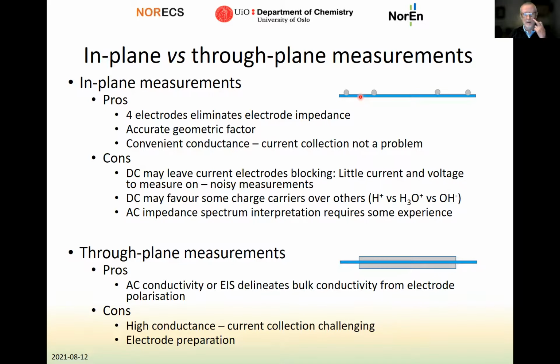So in an in-plane measurement, you can do a 4-electrode measurement. You supply the current here and here, and you measure the voltage here and here. This is a very well-controlled geometry, and it has several pros: 4 electrodes eliminates, in principle, the electrode impedance. It has an accurate geometric factor, and it allows you to measure with quite a convenient conductance range, so it's not a problem with current collection, for instance.